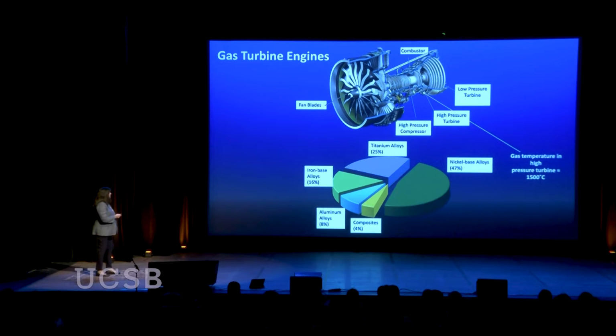Now let's turn to the gas turbine engine. These are composed of basically 4 sections. We have a fan, we have a compressor, we have combustion, and then we have a turbine. Up here we compress air through the fan and the compressor. That high pressure air goes into the combustor with fuel, and then we have very high pressure, high temperature gases coming into the most critical part of the engine, the high pressure turbine. In that section of the engine, the hot gases are at about 1500 C. And if you're flying, say, in a salt environment, you may have residues of various sorts that come along with that hot gas.